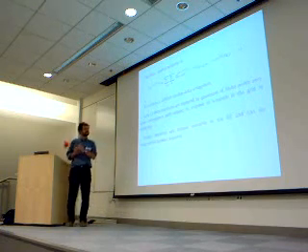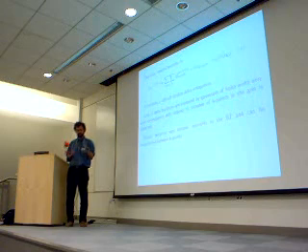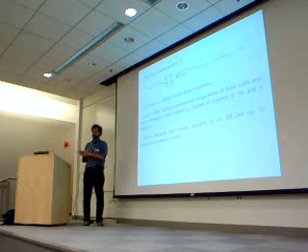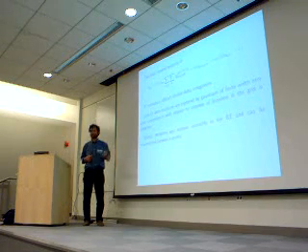This afternoon we will start from a rather small smearing, 0.005, so 5 milli-Rydberg smearing, and go up to 50 milli-Rydberg smearing, with a rather dense grid, 16 by 16 by 16 points in the Brillouin zone of aluminum.